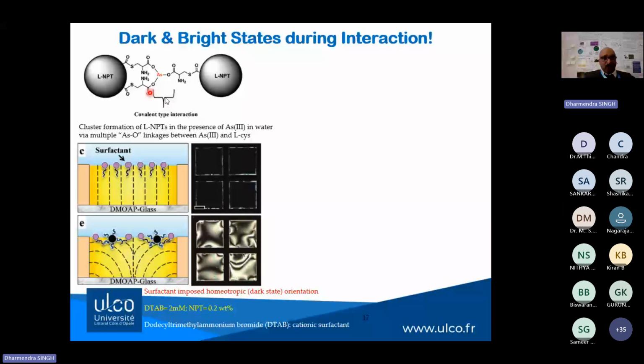We have done plenty of experiments to show that we have selective detection like that. Here we also use one surfactant. The surfactant imposes homeotropic orientation on the liquid crystal molecules, and we have taken DTAB as the surfactant.